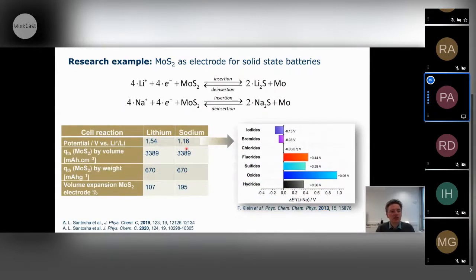You can do this calculation not only for sulfides, but also for hydrides, oxides, and so on. If you look at oxides, for example, the lithium version of the cell would always be almost 1 volt higher. You can see this in metal-air batteries, for example. For sulfides, the lithium version also gives a higher voltage. So it seems that lithium always gives a higher cell voltage. But you can see for chlorides, there's no difference in voltage between lithium and sodium cells. And if you went to conversion reactions with bromides and iodides, then the sodium cell would have a higher voltage compared to the lithium cell. This is actually counterintuitive, but indeed, sometimes sodium cells can have a higher voltage compared to lithium cells.